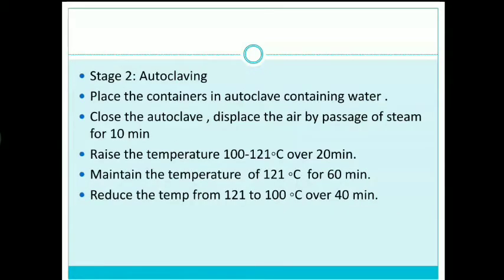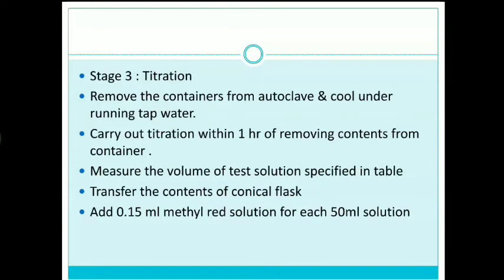Then the second stage is autoclaving. Place the containers in an autoclave containing water. Close the autoclave, displace the air by passage of steam for 10 minutes, and then maintain the temperature of 121 degrees Celsius for 60 minutes.